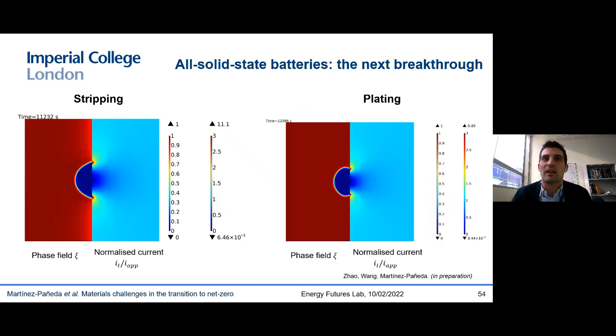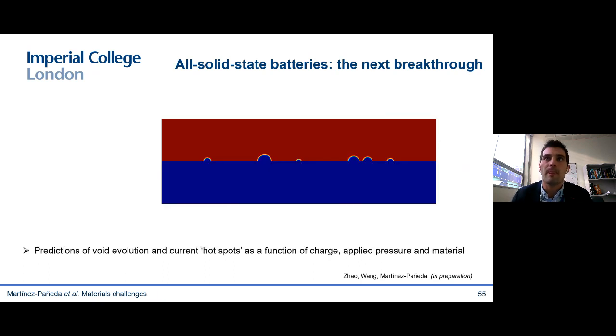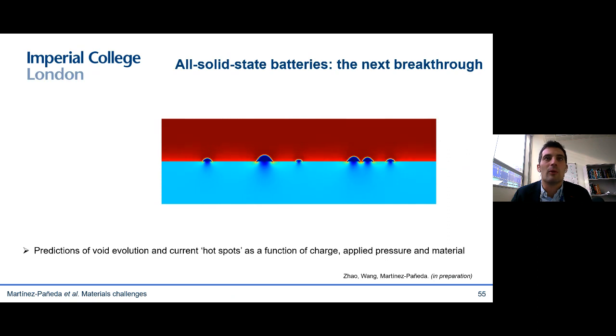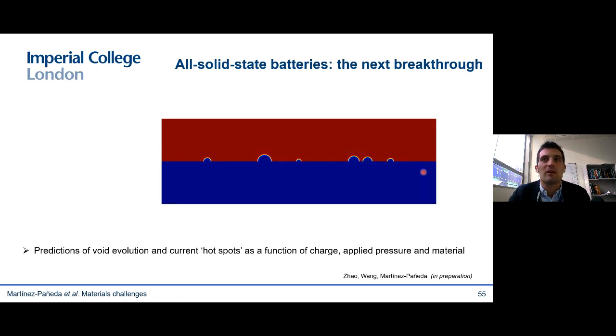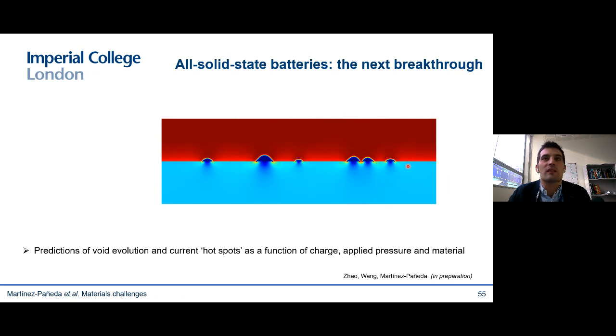And in plating, you see kind of the opposite effect in a way. You are depositing lithium, so you are seeing how the void shrinks, again, as we see in the experiments. And eventually we even see void occlusion, which is something that has been also observed experimentally. And finally, let me show a more realistic scenario where we have multiple voids undergoing multiple cycles of plating and stripping. And here you can see as in the experiments, phenomena such as void coalescence or the shrinking of voids due to the application of pressure and creep deformation.